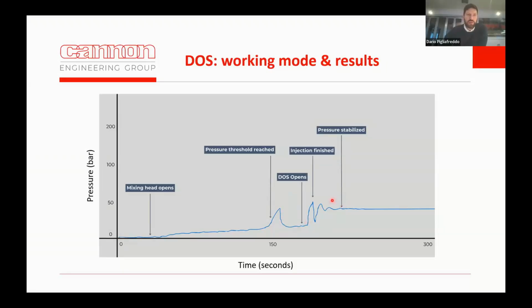At a certain point, the space in the DOS will also finish, and you will have a second pressure peak in this position. You close the injection head, and then you let the dynamic overpacking system do the work again, and it will maintain the pressure at a value that we define, in this case, for example, 40 to 50 bar.